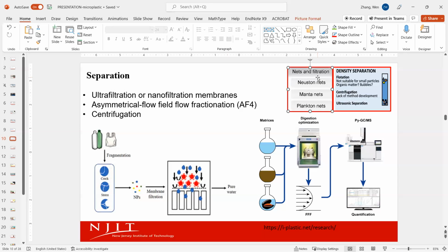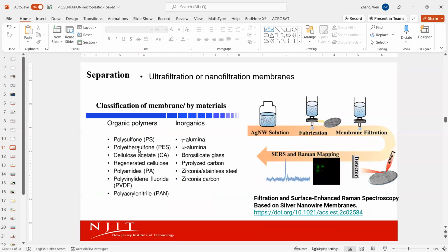And even though they're captured, you probably know that for the membrane filtration, there are a lot of materials. Actually here, this table shows you the membrane filters are made of polymers, right? They could be made of polysulfones, PES, CA, polyamides. Those are basically polymer fragments or microplastics that we are dealing with. So it's not a good idea to use those organic polymer-based filters, because those filters will generate quite strong signals when you analyze them under Raman or FTIR.